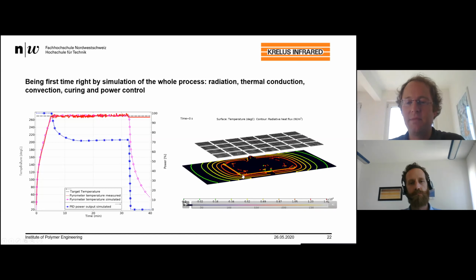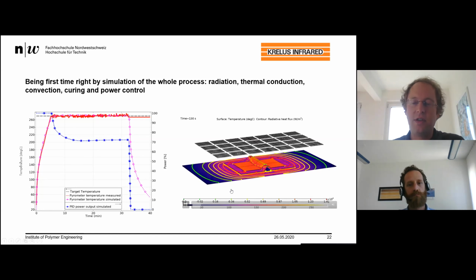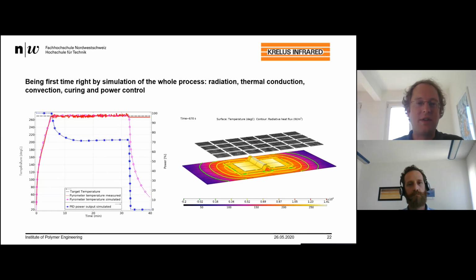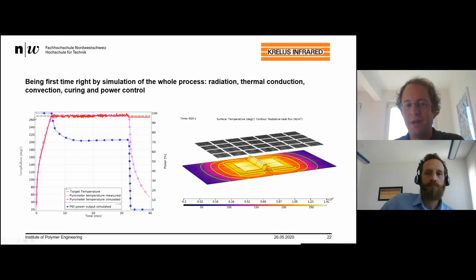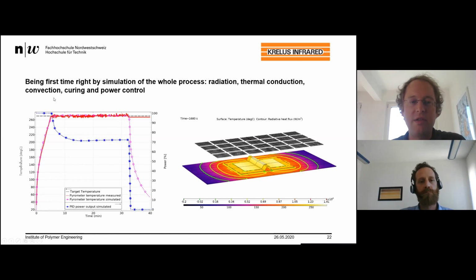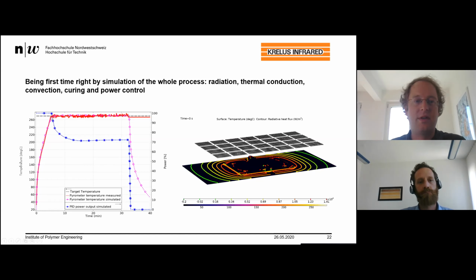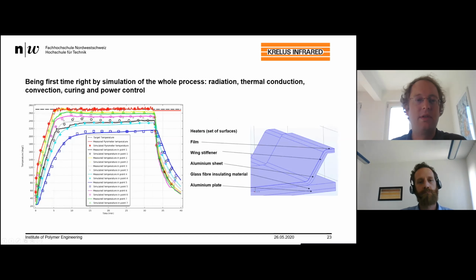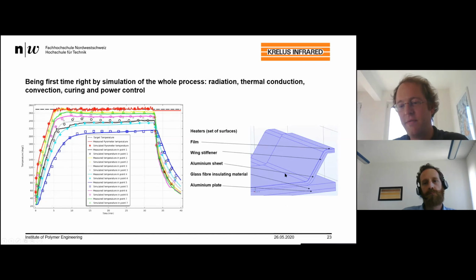So this resin system which we use in this part is really special and has a huge exothermal energy if you cure it in the autoclave. So this process is not possible in a convection oven, because you will create a huge exothermal reaction, as you are accelerating the reaction really strongly. And then heat is generated, and normally a convection-based system is so slow that you cannot get rid of this heat flow. But our system is capable because it reacts really, really fast. And this is visible also in these curves, which represent the temperature at different positions through the thickness.